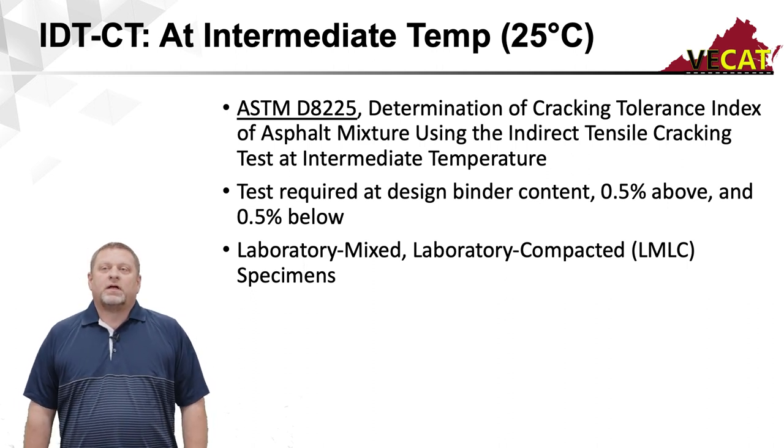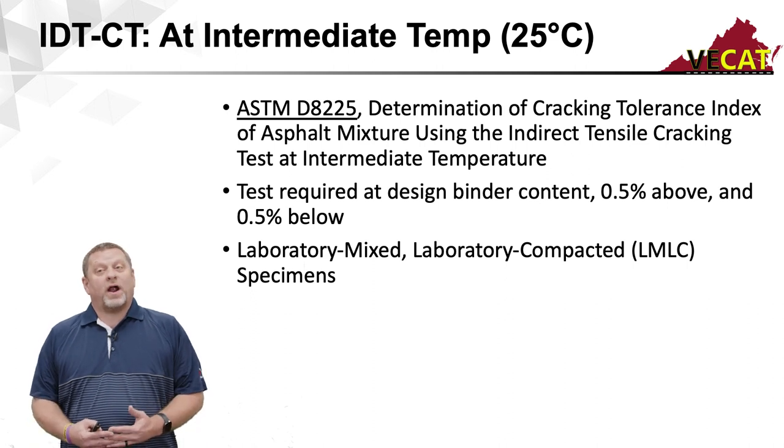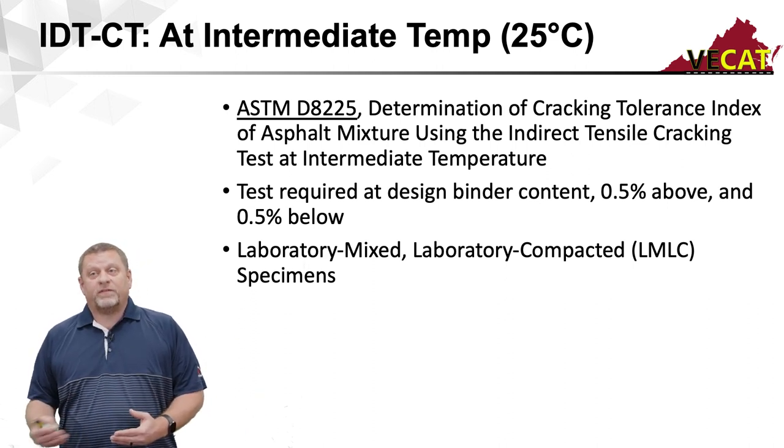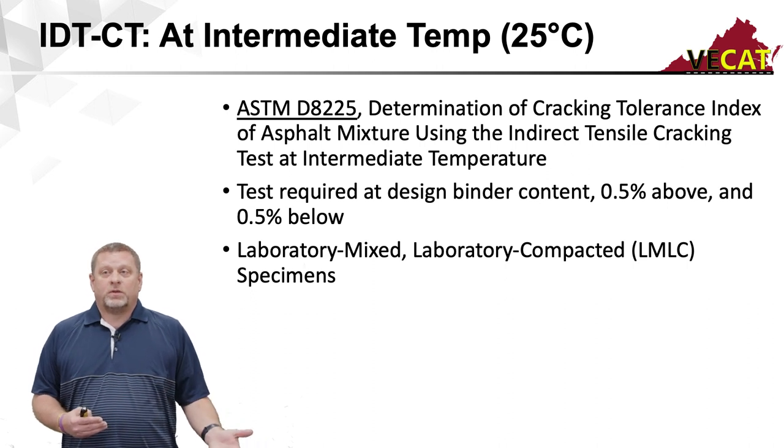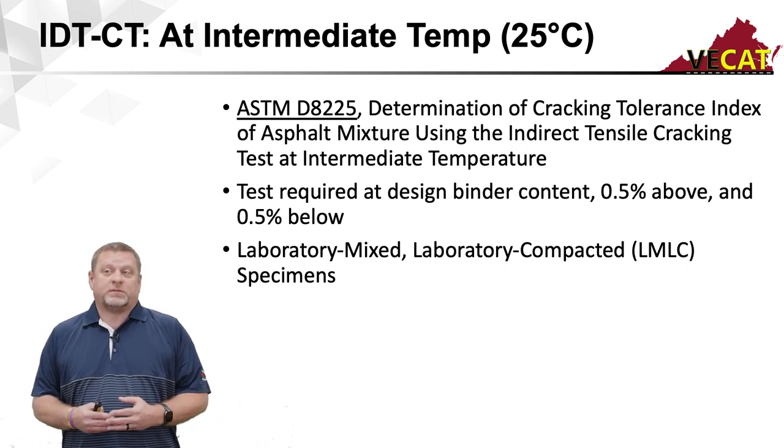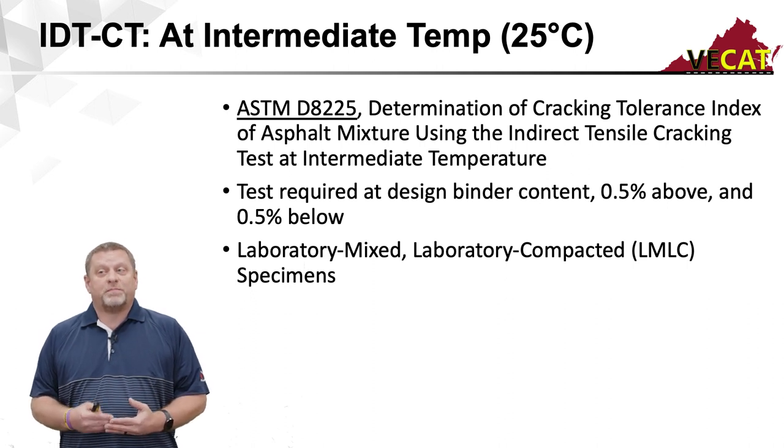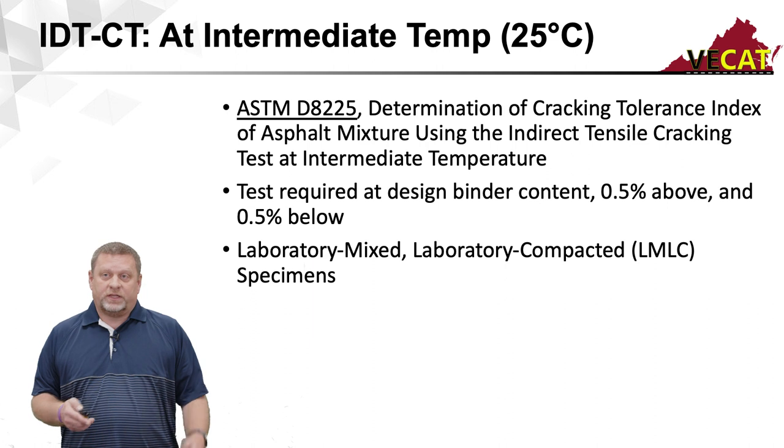It's a mouthful. This test is required during the design phase to be done at the design asphalt content that we established with the volumetrics, at 0.5% above and 0.5% below. So right here is 15 additional specimens. And these are all going to be laboratory mix, laboratory compacted specimens, individually done.